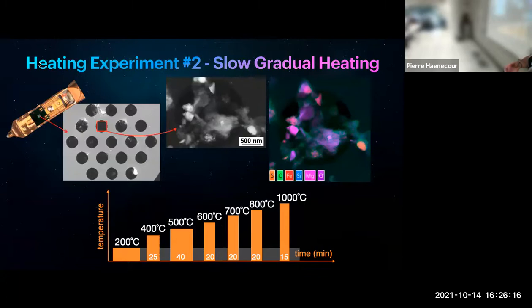The second experiment that we did afterwards was to try to replicate a similar heating using a similar sample. It's not the exact same sample, but it's the same meteorite loaded on another heating chip. If you look before heating, here is an image of the sample and the elemental maps. You can see it's similar, showing iron, magnesium silicates, organic matter, and some sulfide and iron metal.